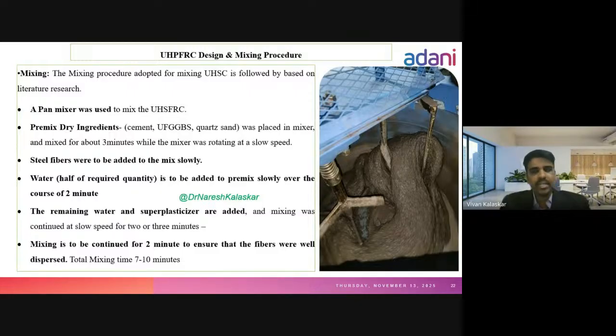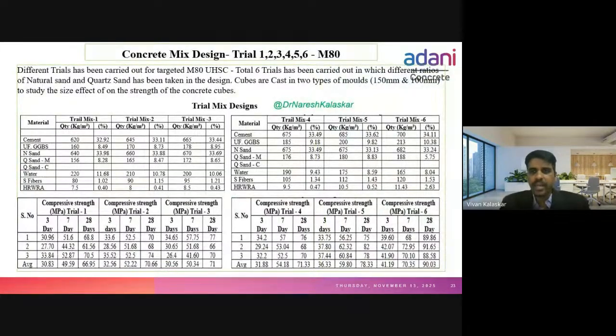So that the steel fibers will be perfectly mixed. The total mixing time will be around 10 minutes, so that you will get an excellent mix. So this is the M80 grade of concrete.